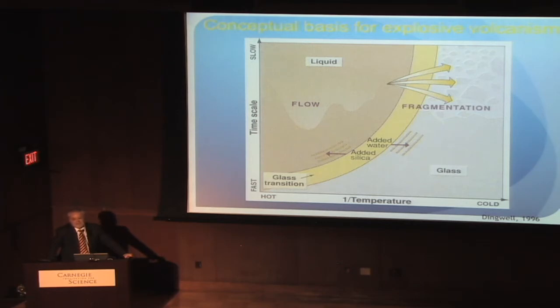The simple observational fact is that volcanic ash, one of the most common products of explosive eruptions, consists in most cases of a matrix of broken glass. It has knife-edge shards with surfaces that represent former bubble walls and so on and so forth. It's as if somebody took a hammer or a mortar and pestle to a rock and crushed it up and produced broken fragments. Yet the flow which caused this has been a viscous system, multi-phase system, flowing up a plug, flowing up a conduit, and pouring up at a certain point until it can no longer flow. And because these silicate liquids that we're looking at depth flow in the beginning and break in the end, we can be absolutely conclusively sure that they've gone through the glass transition.